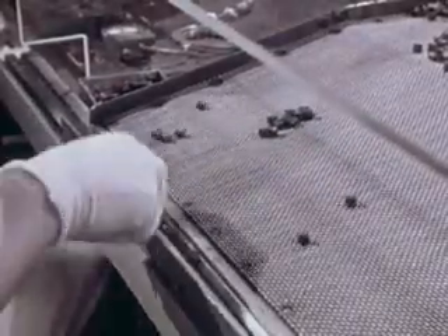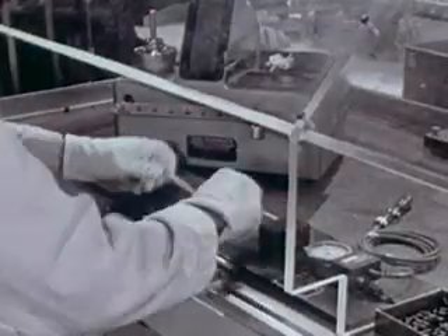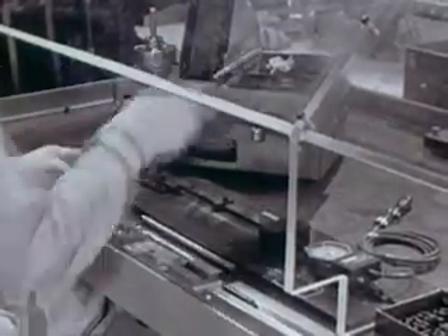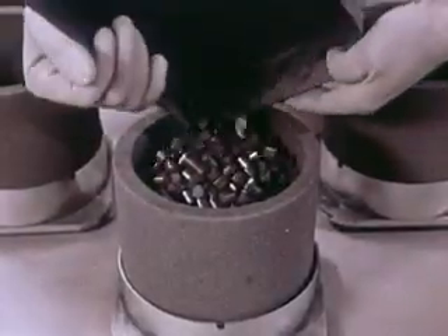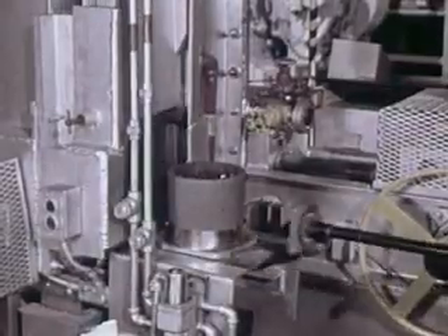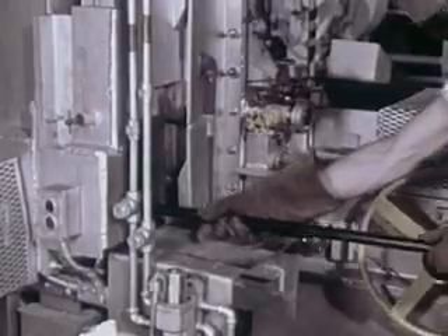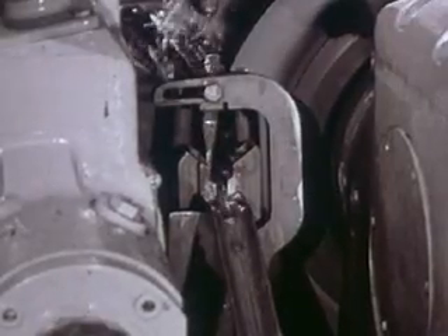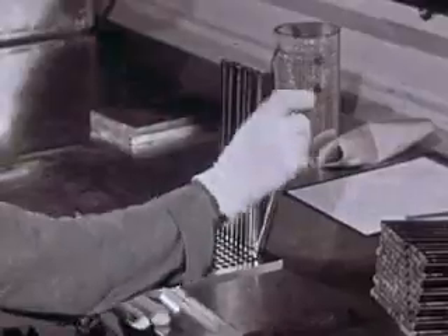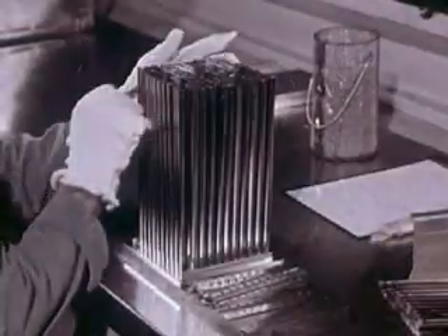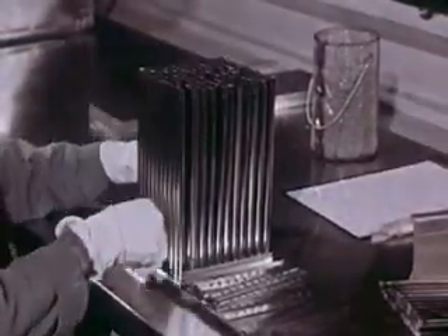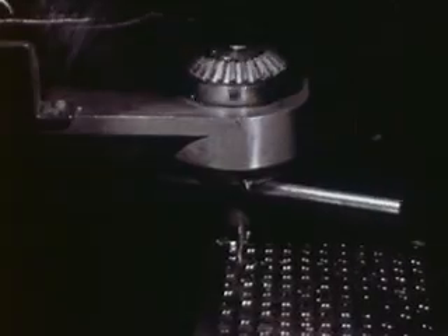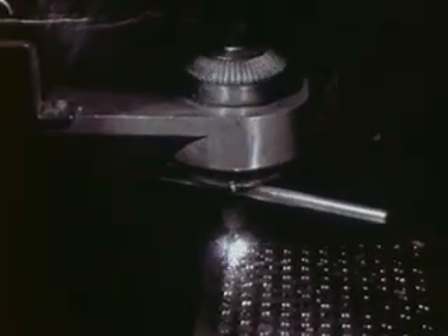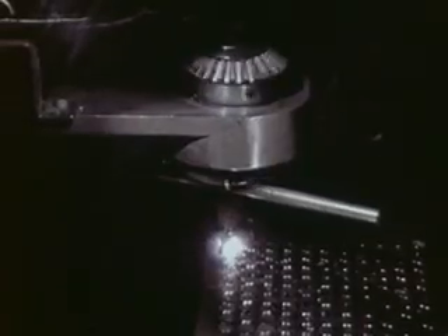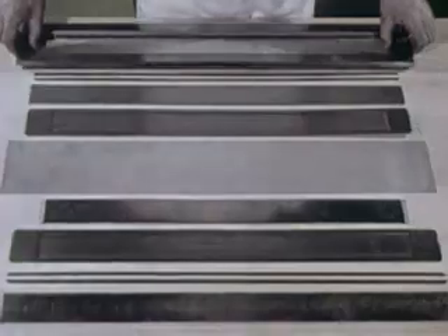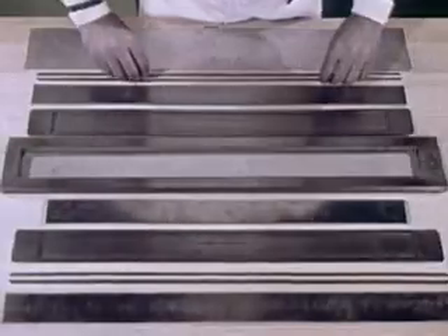More than 2 million uranium oxide pellets and 95,000 blanket tubes were made. Processing of pellets included agglomerating, compacting, sintering, and grinding. Fuel rods and bundles were assembled, argon atmosphere welded, annealed, and machined. In the meantime, seed elements were also being made.